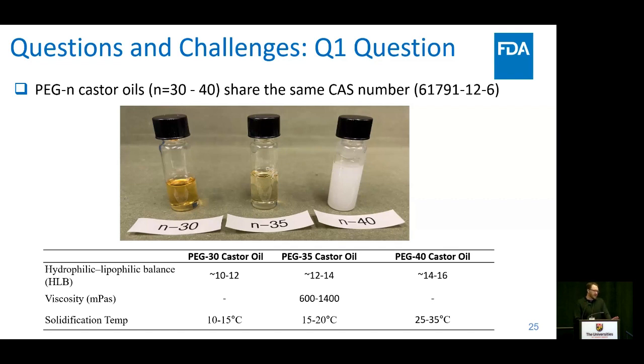But if you are to try and make a formulation using any one of these, it's important to think about those manufacturing considerations as far as what temperatures and what mixing directionalities you're using, because you could do this whole process, say, at a slightly elevated temperature and end up always getting a microemulsion out of the system.